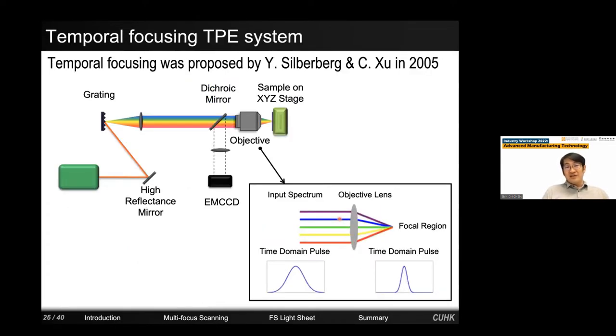In this technique, the so-called temporal focusing technique, we actually exploit and take advantage of the dispersion effect. So the femtosecond laser is brought to an optical grating. As a result, different color spectrums are dispersed. And when dispersion occurs, the laser peak power is lowered and cannot perform multi-photon absorption or excitation effect. Then all these dispersed spectrums are recombined and only at the focal region they are overlapping. As a result, it forms a thin light sheet at the focal region, and right after the focal region, the light becomes dispersed again.